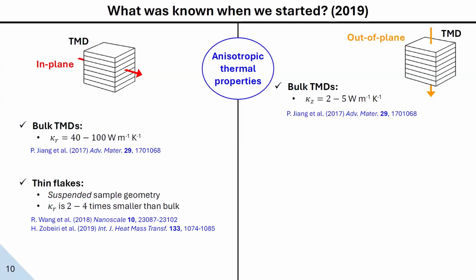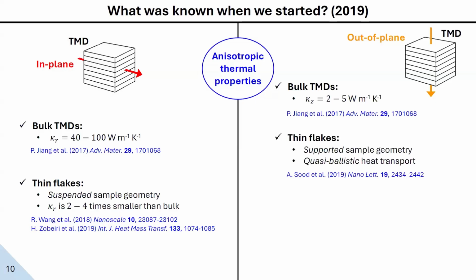The thermal conductivity slightly decreases when we make our materials thinner and thinner, and this is also the same in the out-of-plane direction. For the out-of-plane heat transport experiments, we basically use supported sample geometries where we place our material on a substrate which will act as a heat sink. So we can define a thermal gradient from the top to the bottom of our material. A very important work in this direction is this paper, where they report size effects manifesting as a quasi-ballistic heat transport.